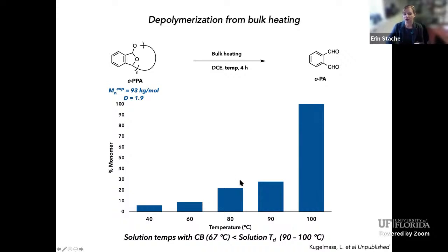Now, in comparison, we've rudimentarily tried to estimate the bulk temperatures that we're reaching through the photothermal effect. And we do see an increase in temperature above room temperature to about 67 degrees C when there's carbon black in solution. But that's still significantly lower than the bulk solution temperature that we need to get effective depolymerization, which means that the surface of the carbon black must be much hotter to actually affect the depolymerization in this 4-hour time scale.